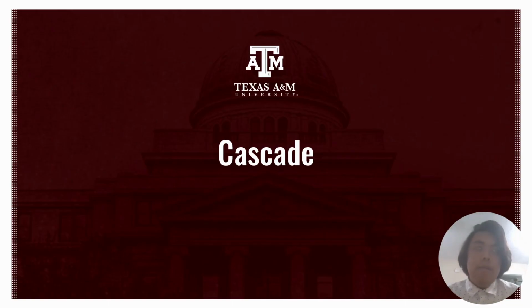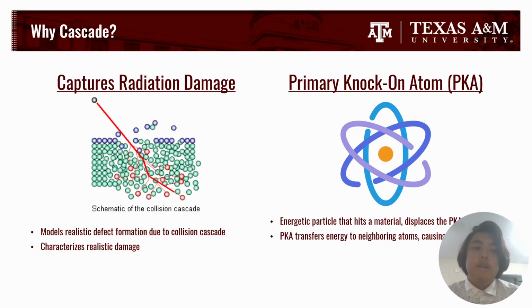So let's talk about cascade molecular dynamics. So what exactly is this? Well, cascade molecular dynamics models radiation damage through the use of a primary knock-on atom, which is the first atom that is displaced by an energetic particle such as neutrons and ions. The way radiation damage works is a high energy particle will collide with the lattice, which causes a chain reaction of atomic displacement, also known as a cascade, which is what cascade molecular dynamics models.